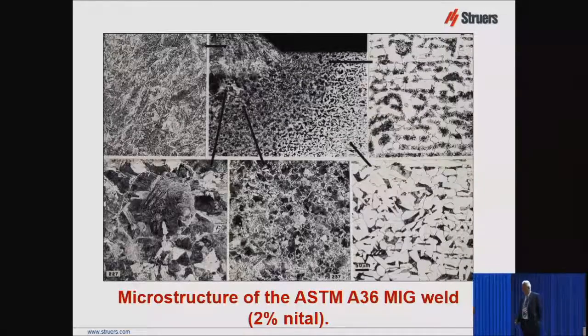Here's our weld metal up here, the fusion line, the heat affected zone, and down here is the base metal. Here's the original base metal, longitudinal plane. This is the beginning of the heat affected zone, and what you're seeing is the pearlite that's in the base metal is starting to go into dissolution. And then reprecipitate, and it's not a lamellar structure anymore.